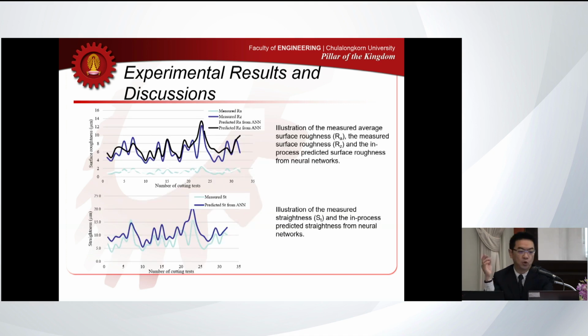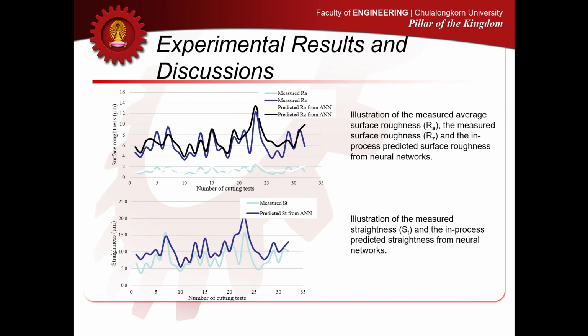Again, this shows you the result from the new cutting condition. The above graph shows the roughness, Rz and Ra, the maximum peak and the average roughness. You can see that the measured and the predicted are close together. Even the straightness in the lower graph, the predicted and the measured are close together, but somehow a bit far because this cutting condition is out of the range you trained it on before. But anyway, this predicted value is acceptable because it is close to the measured one within plus and minus 10% error.